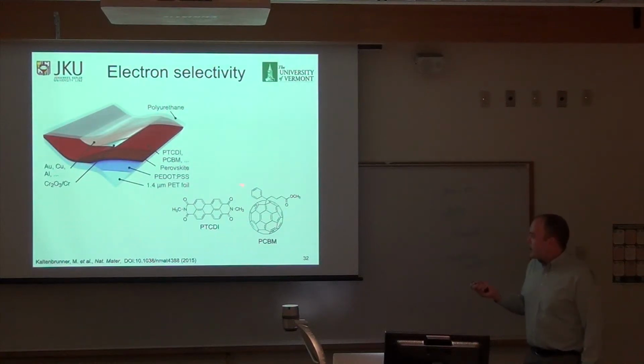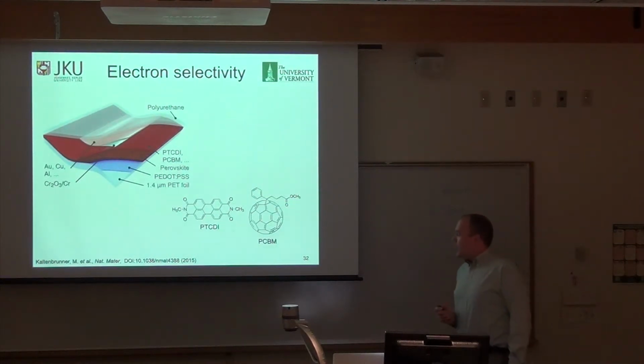And we selected this material, which is a very old N-type organic semiconductor called PTCDI. This is a red pigment that's found in a lot of cosmetic products and paints, and it's very stable - you can leave this stuff in air in the lab for decades and it doesn't bleach, it's fine, very good rock solid stuff. It works as well or better than PCBM did, so for us it was a no-brainer to just use this PTCDI as an electron selective capping contact on top of the perovskite.